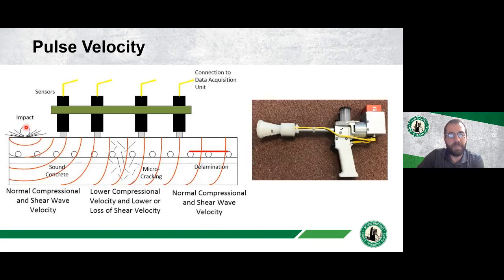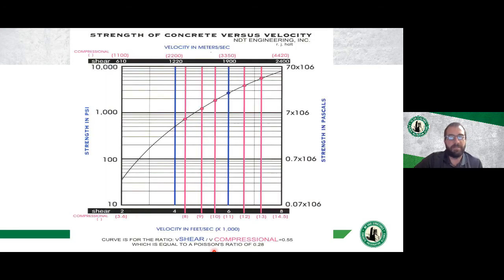In addition to the waves bouncing in the vertical direction, the waves will also travel horizontally. And so we can get a wave speed based on the position of our sensors, because we know the spacing between those sensors. So the wave speed will tell us a lot about the concrete quality. Especially if there's microcracking, that'll slow the wave down. And so we're able to identify the in-situ concrete compressive strength based on the wave velocity. And so here is strength in PSI, and then here's the velocity of the wave. And as the wave velocity increases, the strength of the concrete also increases. And so by measuring the wave velocity, we can identify what the strength is in PSI.